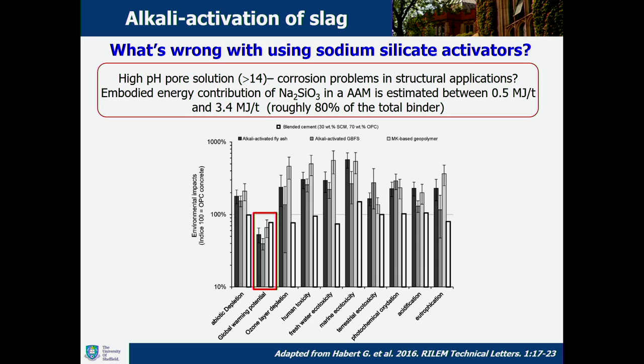One of the first things is that we reach really high pH within the pore solutions when we use sodium silicate activators. Nowadays, we really don't understand how corrosion will take place when we have steel rebars embedded within this type of concrete. So it would be unfair for me to say that because we have a very high pH, it will corrode. It's something we really don't understand, because the chemistry of these cements is much more complex than that. But the second thing that is also calling my attention personally is the fact that roughly 80% of the embodied energy that is typically allocated to an alkali activated cement corresponds to the sodium silicate activator, which is quite concerning, because one of the drivers to develop this type of materials is that they are tremendously environmentally friendly, that green cement and so on. So the question is, can we make it greener?